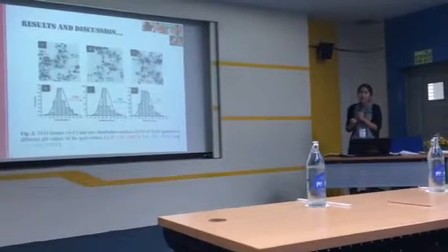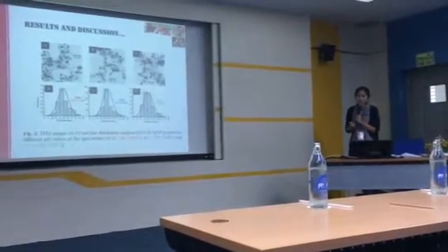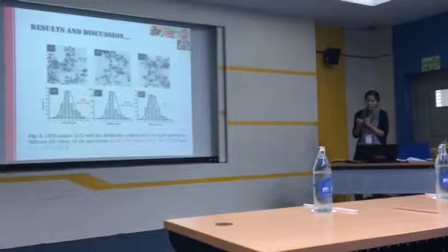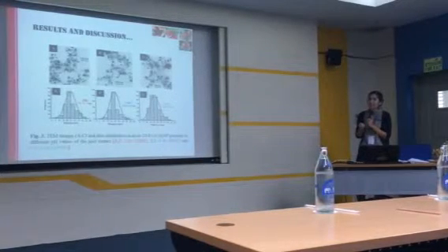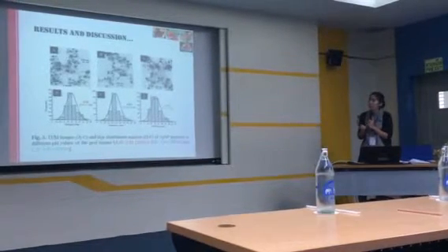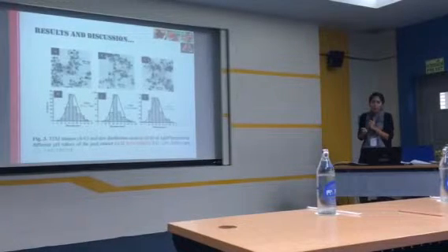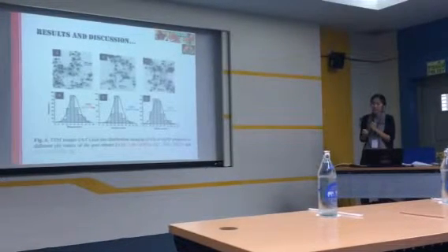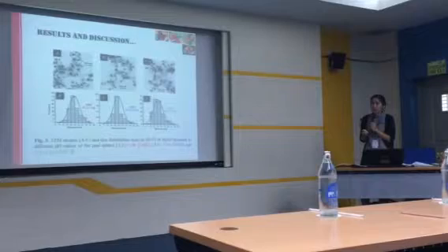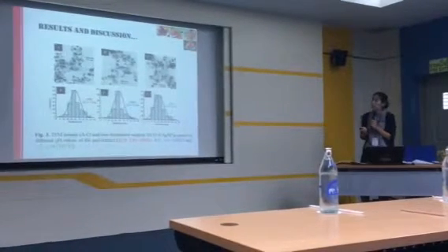The average size of the silver nanoparticles is reported. The result suggests that the average size reduced with increased pH, which was consistent with the blue shift of the absorption peak in the UV spectrum.